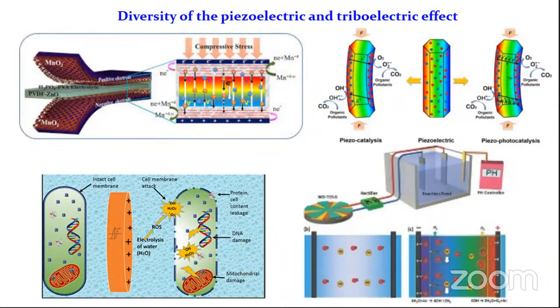As you can see in the first figure, there is a self-powered energy system, where we have used a piezoelectric separator, which governs the electron and ionic movement in the supercapacitor. In the second figure, we have seen that piezoelectricity enhances the catalysis of several organic pollutants. When it is piezocatalysis, the piezoelectric potential will work. But when it is piezophotocatalysis, piezo and photon will work together. So what happens in piezophotocatalysis? When photons irradiate the surface of the materials, there will be some electron-hole separation. That electron-hole separation has a short lifetime. So to stabilize that electron-hole separation, we have applied the piezo potential.